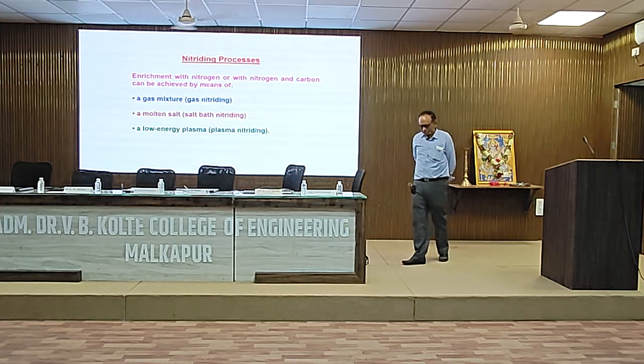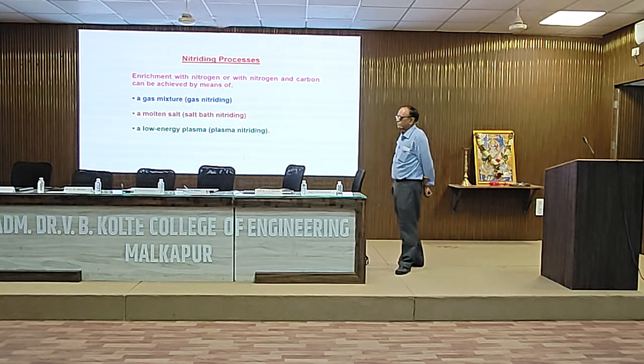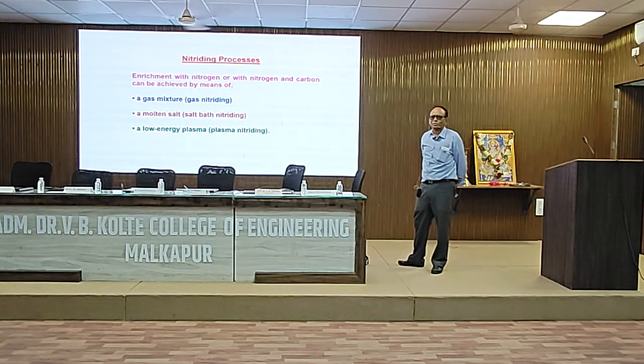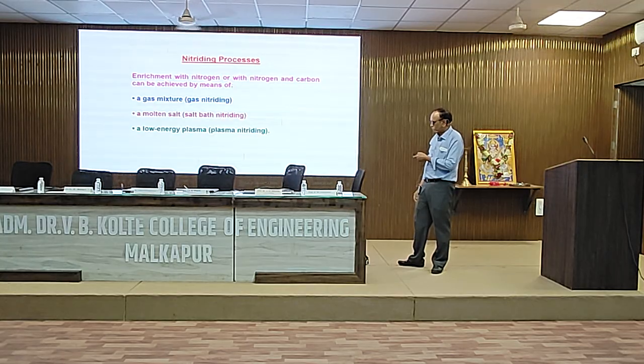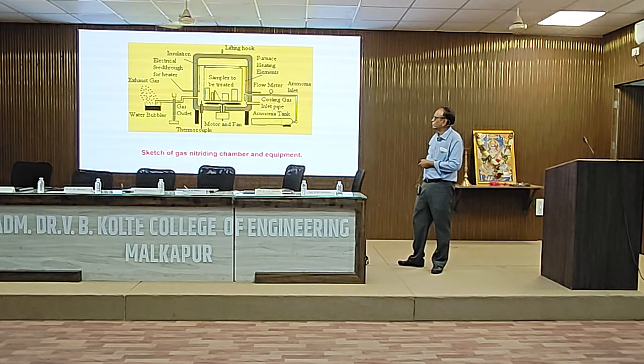Basically, in this nitriding process, three processes were used. Gas nitriding, in which ammonia is decomposed catalytically onto the steel surface, which is hot. A molten salt bath nitriding, where cyanide mixtures are in a molten state, and components are immersed into that at high temperature. But the cyanides are poisonous compounds, so that process has been environmentally banned. And then the third process is plasma nitriding, low pressure plasma nitriding, that is the one which is used.